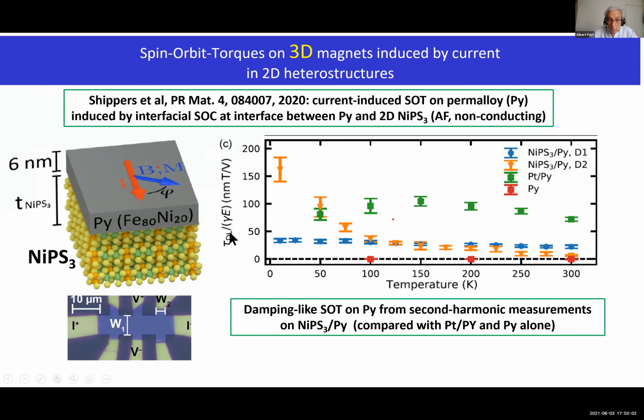You can see, for example, some measurements of the torque measured by second harmonic measurements. You can see the torque exerted on the magnetization of permalloy is this one. And so, of course, it's very important to compare with the torque exerted where you replace these 2D magnets by a 3D material, platinum. This corresponds to the green dots here. You can see that at low temperature, of course, the effect obtained with these 2D magnets and with the 2D electron gas at the interface of this insulating 2D magnet has better performance than for platinum only.